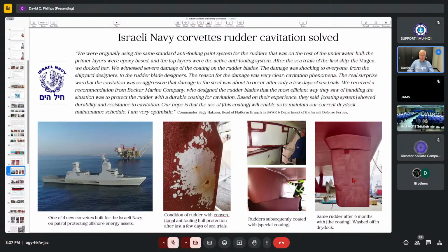And it's undamaged. They did coat it very well, by the way. Not only did they prepare it properly, they put on 2 coats of this coating, but they also did a stripe coat over the welds, which means an additional coat of paint goes on in between coats for the areas that are likely to suffer damage.